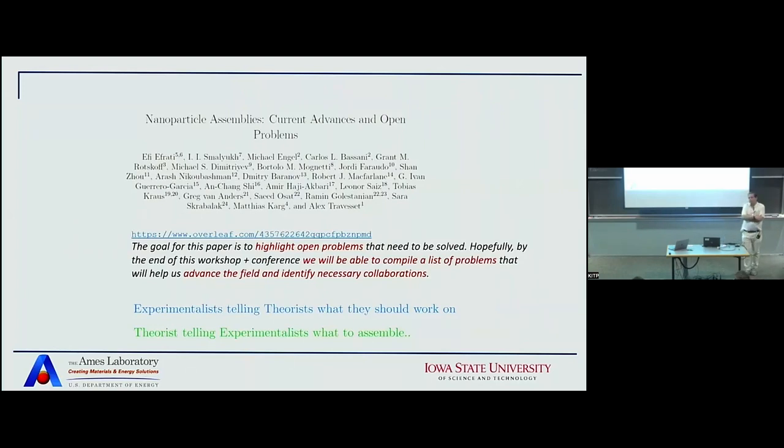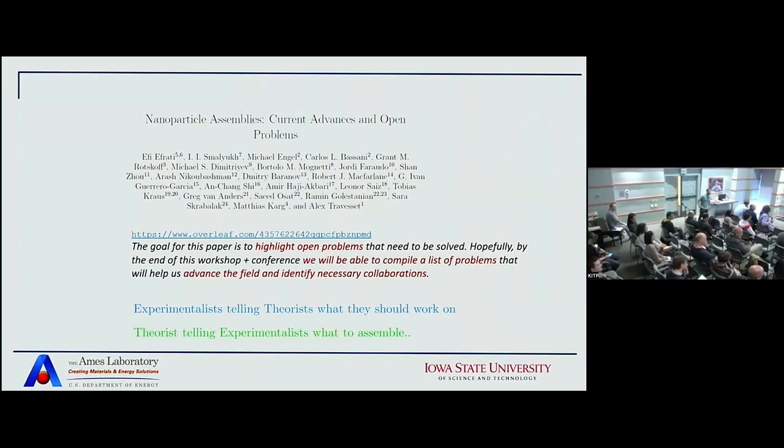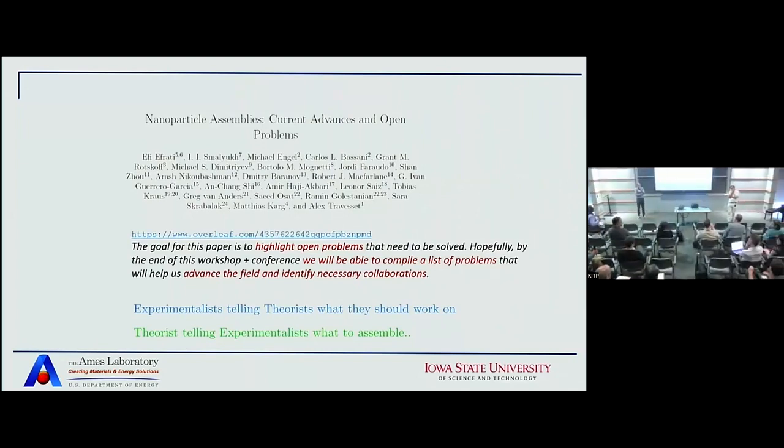David Limmer, UC Berkeley. Thank you for the very clear talk. I am very sympathetic to the idea of trying to determine an effective hard sphere size and then correct the energetics away from that. Along those lines, I'm wondering if you have compared the hard sphere diameters you've arrived at through geometric arguments to those used long ago in liquid state theory, from the WCA theory of liquids, where after you subtract out the slowly varying attraction, you look for where the Boltzmann factor from a reference hard sphere fluid best reproduces the Boltzmann factor from the full system. That's a unique definition motivated from statistical mechanics instead of geometry.